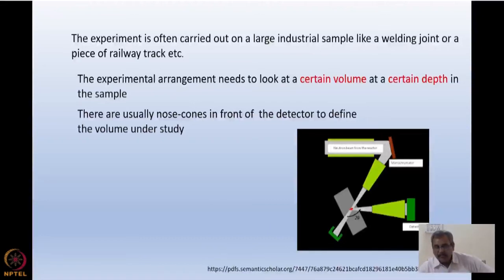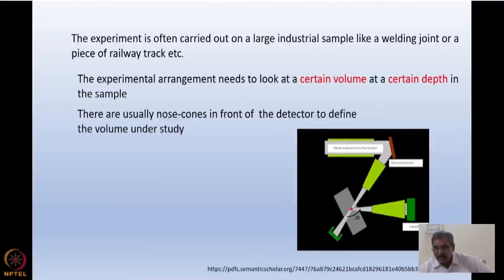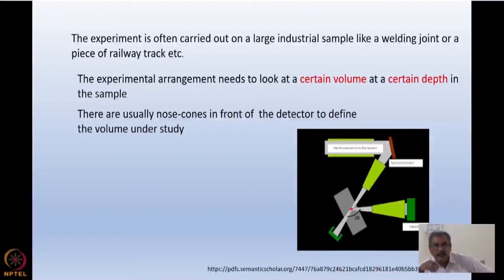D₀ is determined either if we know a part of the sample is strain-free — for example, when detecting strain around a welding joint, we go 5, 10, or 20 cm away from the joint, measure the d-spacing there, and take that as D₀. We then compare it with the d-spacing from the volume around the welding joint, and by sliding, rotating, and translating the sample we can map the strain values across and away from the welding joint.